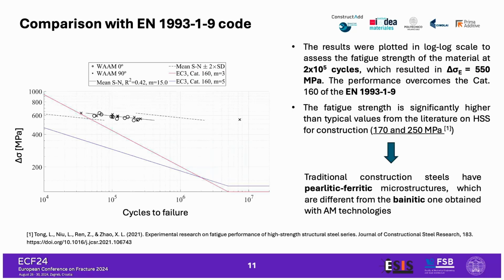And if we compare our points to this limit, to these reference curves given by the Eurocode, we see that the performance of our steel is incredibly high with respect to these reference values. And the same we saw in the literature. So I reported a reference work by Tong et al. that tested in the same conditions high strength steel series, so different high strength steels in the same condition, and the delta sigma C that they assessed at 2 by 10^5 cycles, being 550 megapascal in our case, was in the range of 170 to 250 megapascal.